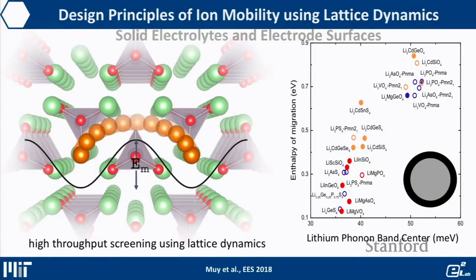What is really the parameter or physical origin that influences the conductivity of, for example, the LISICON structure? You can see that the conductivity varies by 10 orders of magnitude. And what we find recently is that if you look at the phonon energy, the phonon density of states, right? So essentially how fast the lattice would vibrate is coupled with the energy barrier that lithium will move through the lattice, right?